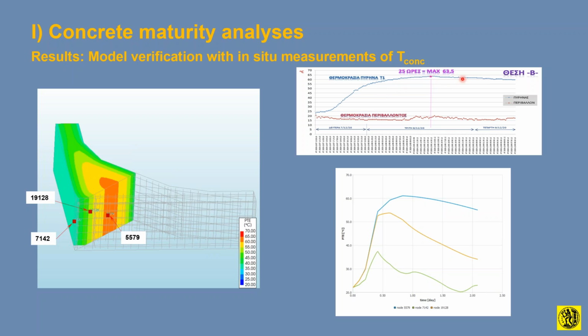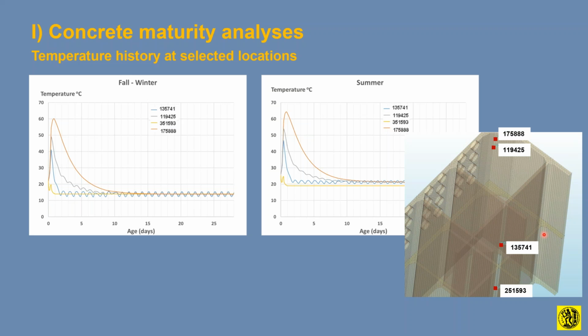So we were fairly close to the temperature gain of the in situ measurement using Diana and the standardized material properties for the same concrete grade. So we went ahead and did the maturity analysis. Now, in the two different scenarios, the fall and the summer conditions, we can see temperatures generated in different locations of the entire caisson quadrant.